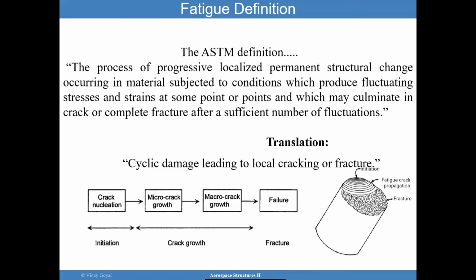Another point I want to consider here is that if you have taken a little aluminum wire, like a clip, and you have bent that clip back and forth, you will see that if you apply very little fluctuation, it's unlikely you will break the clip. But if you apply a significant amount of fluctuation and you plastically deform the clip, it will take very few cycles to break the clip. And so, as you can see there, the amplitude matters, and also the number of cycles. If you cycle something for a long time, it's more likely to fail than if you were to cycle it very few times. And so, if I were to translate what the ASTM is telling us,